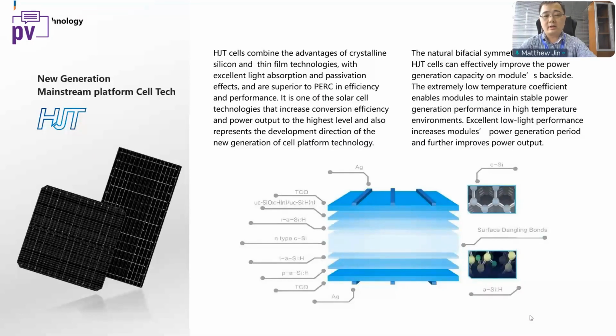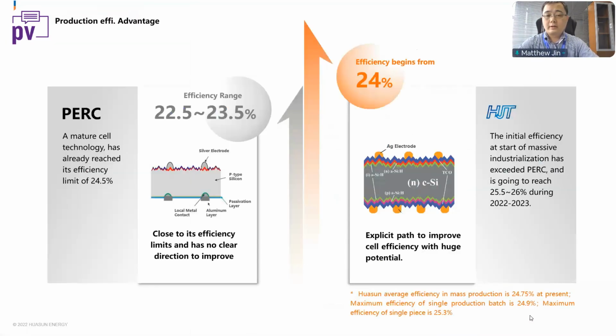So for the HJT technology, the new generation, compared with the PERC technology, HJT has many advantages, but also for the future, HJT is a good platform, especially combined with the tandem cell technology, which can get much higher efficiency and a better cost compared with the present PERC technology. For the massive production advantage, especially on the efficiency, compared with the PERC, which is around 23%, the HJT cells start from 24%. For the Huasun team, our average efficiency in mass production is reaching 24.7%. And our target is to reach 25% around the end of this year, and 25.5% in 2023.